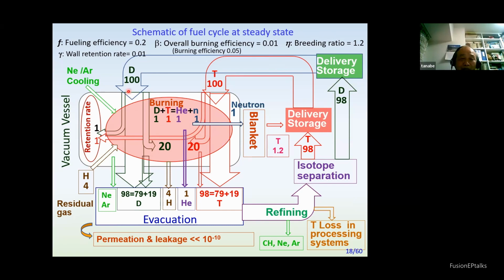Assuming this wall retention, so 1 is going to the walls and removed. Then we recover 98. So 1, 2 are removed then coming back, meaning we only recover 98. So if the breeding rate is 1.2, this does not satisfy the 100, meaning tritium self-sufficiency is not attained. So we have to increase the burning coefficient, increase the burn of tritium, and also decrease the retention rate.